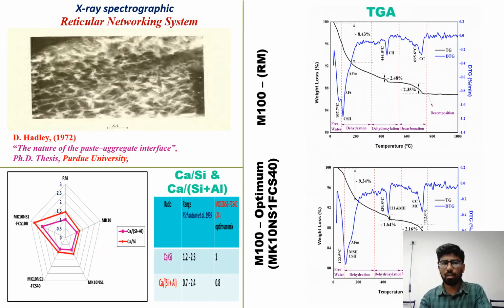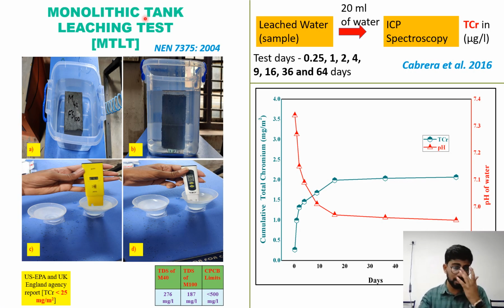And Dr. Hadley in 1972 observed a similar pattern, a reticular networking system. This is the reason why the strength is lost in the complete replacement. Coming to the 60-40 proportion, there is a low calcium silica and calcium silica alumina ratio. And coming to the TGA report, our optimum mix shows low dehydroxylation and decarbonization peaks, and this is the reason for the strength gain.